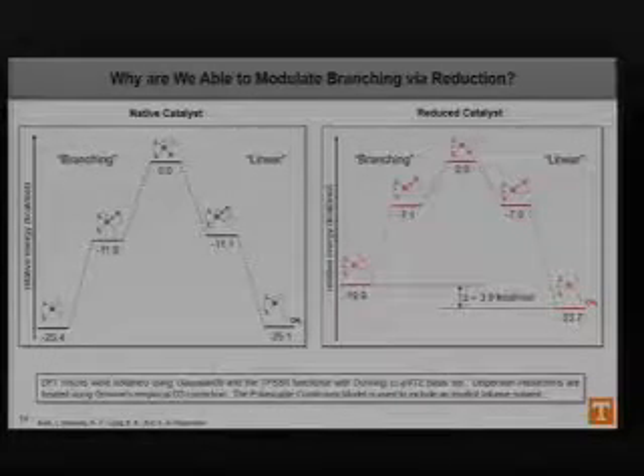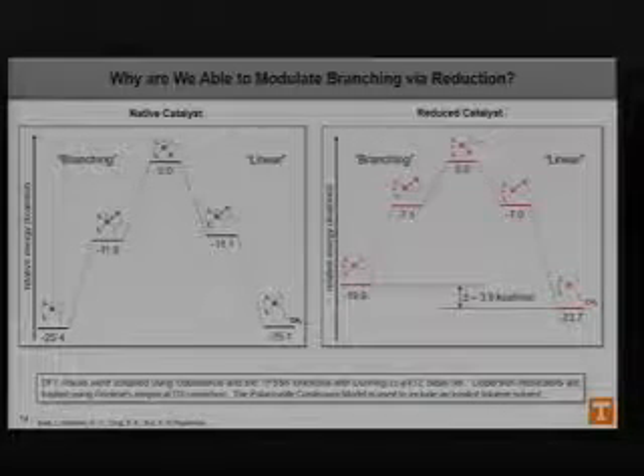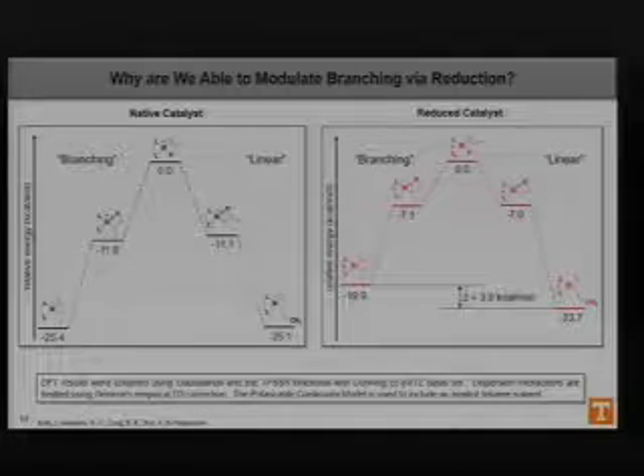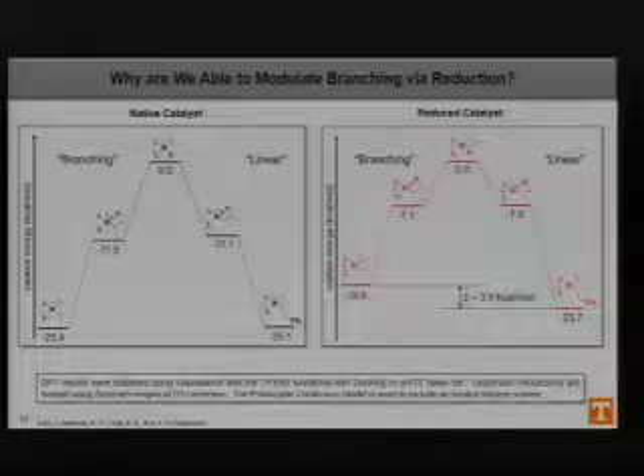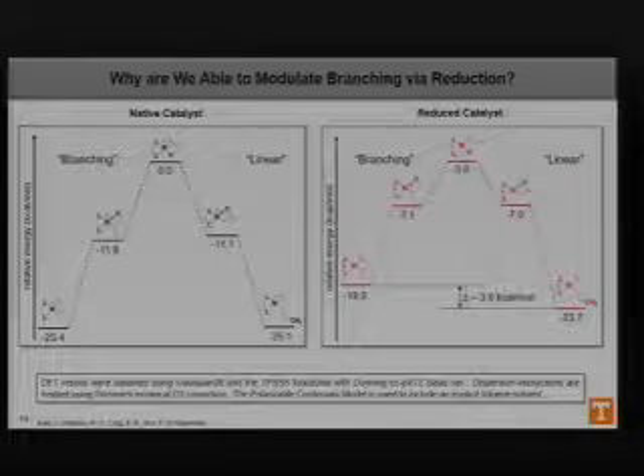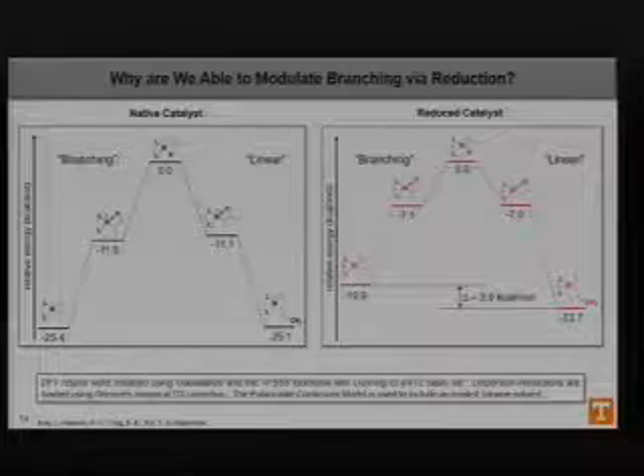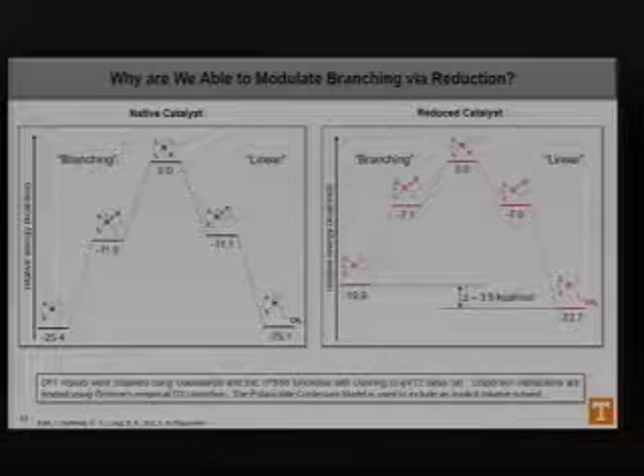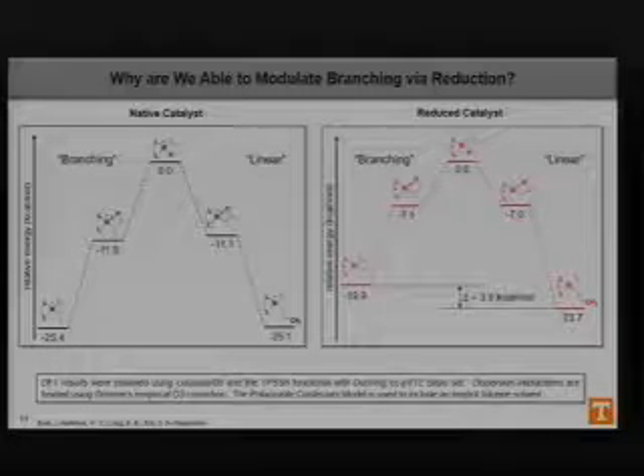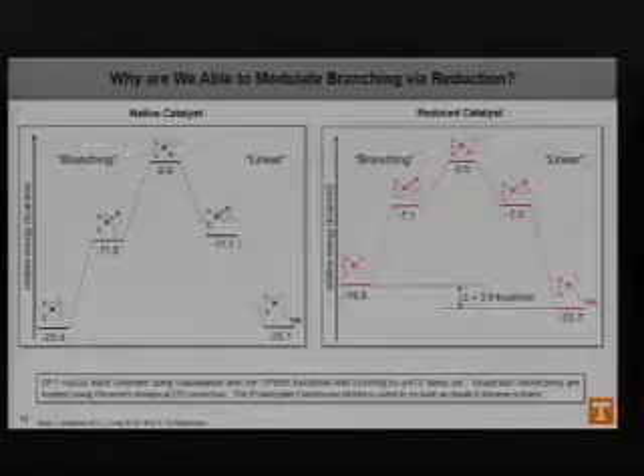So we obtained two energy profiles for both the reduced catalytic species and the native catalyst. And what I have listed here is essentially the pathways leading towards branching and the pathway leading towards linear polymer chain generation. Now, as you can see from the native catalyst, the branching and the linear catalytic species are at negative 25.4 and negative 25.1, downhill in energy. So they aren't significantly different from each other.